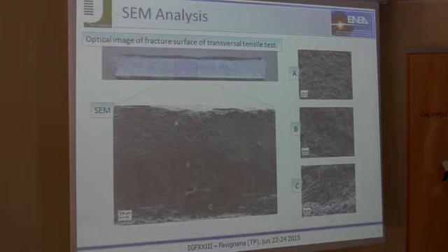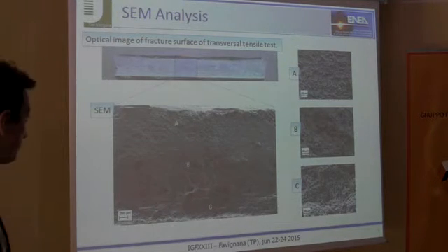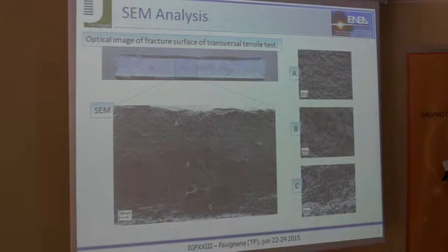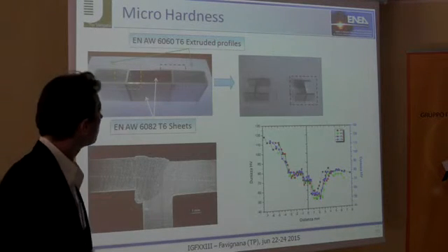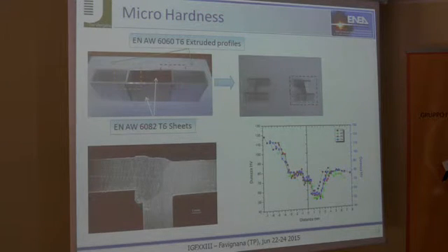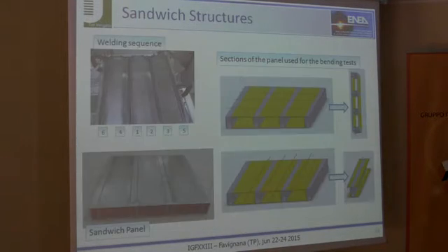Here you can find an optical image of the fracture surface of the transversal tensile test, and the fracture occurred in a ductile way, and in fact it's possible to see the presence of dimples in all the region of the fracture. Micro-hardness tests on the butt joints show the characteristic W-shaped profile, with the lowest hardness value of about 50 HV in the heat affected zone of the extruded profiles.